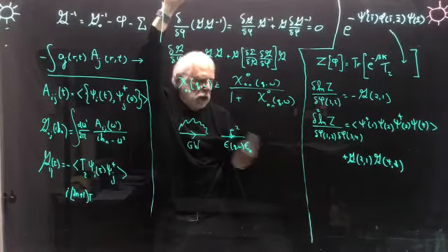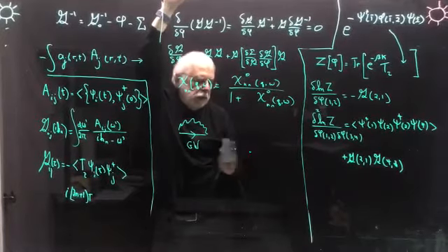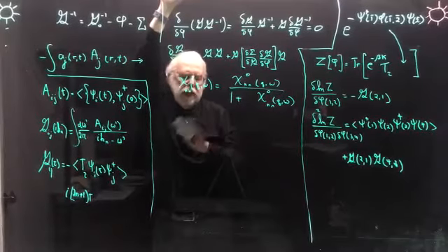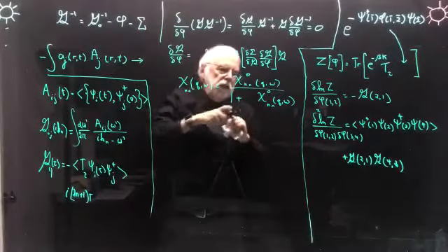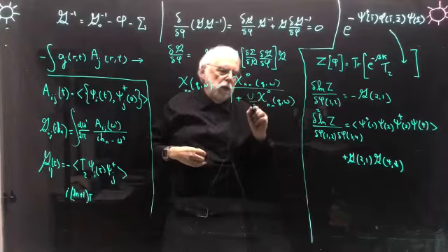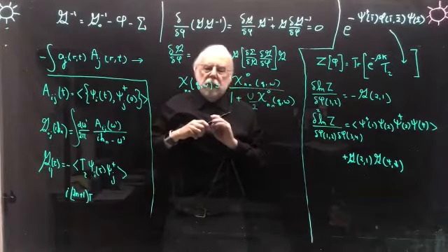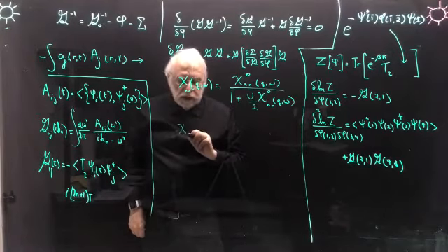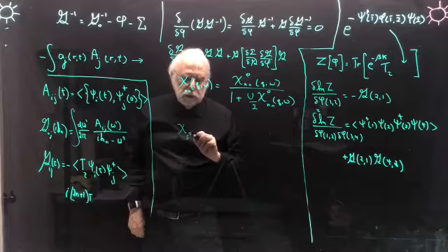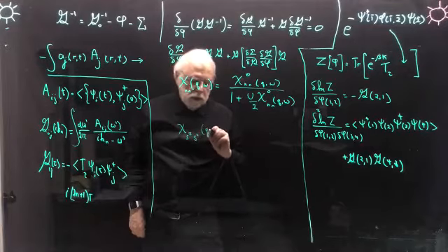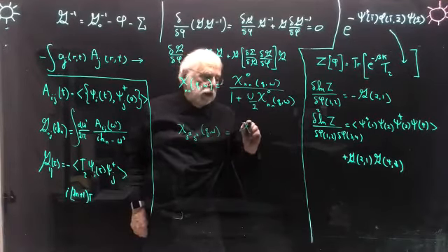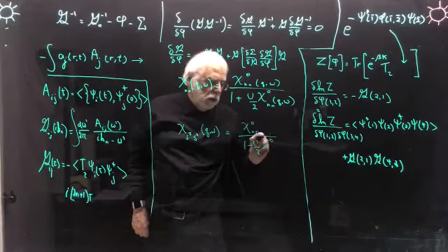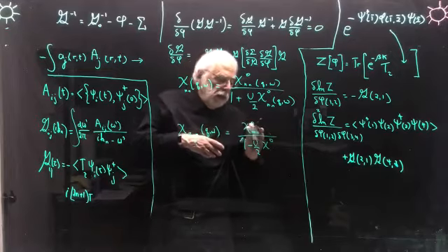Now we go to fermions on a lattice. And for fermions on a lattice, what we find is that the RPA, what we did for the electron gas, so here we would have U over 2, gives a crazy result. This is for charge, and the new quantity that we get is that spin fluctuations become important. And that's because of the Pauli principle. It turns out the chi_0 is the same.